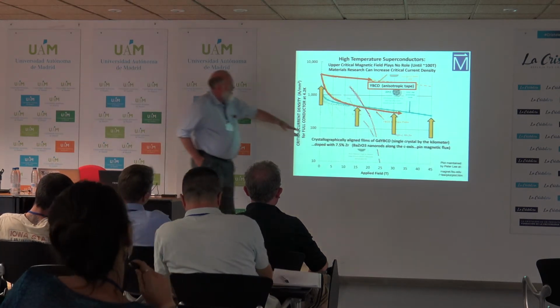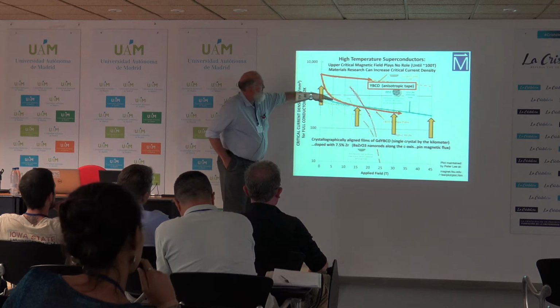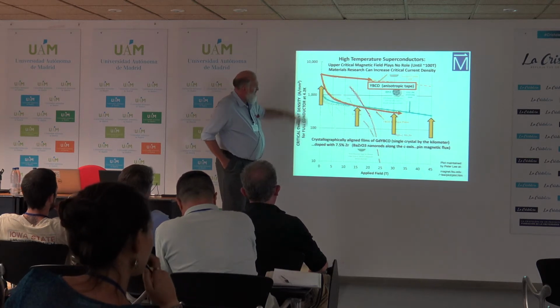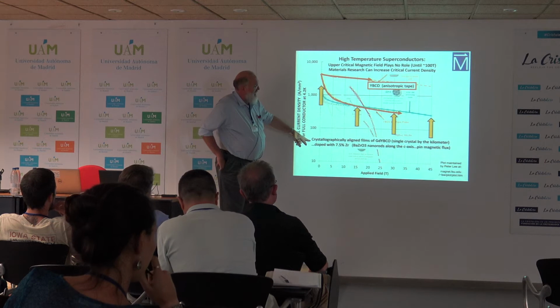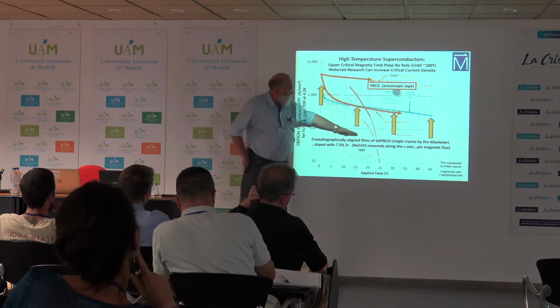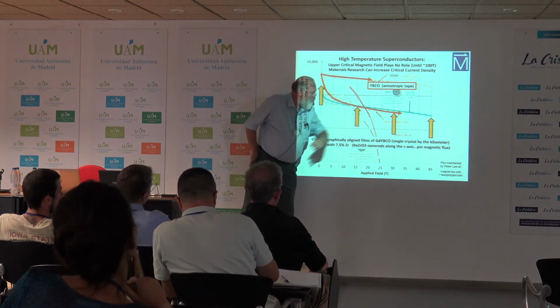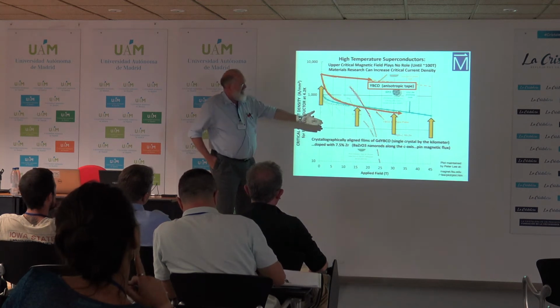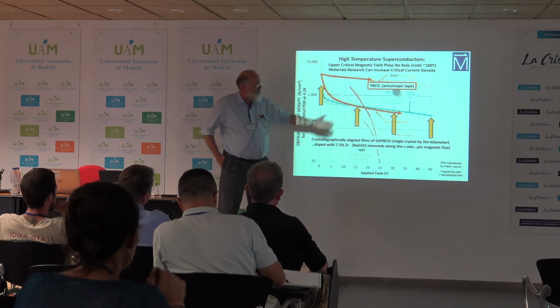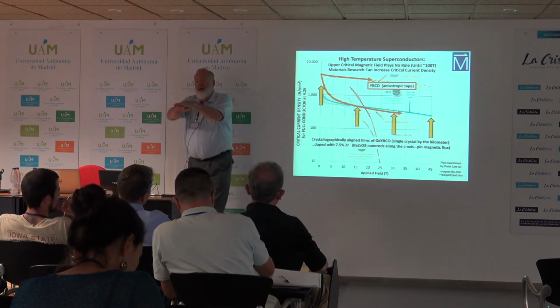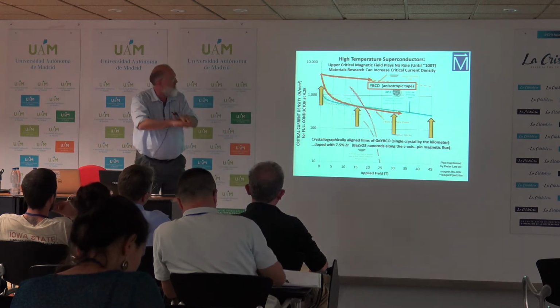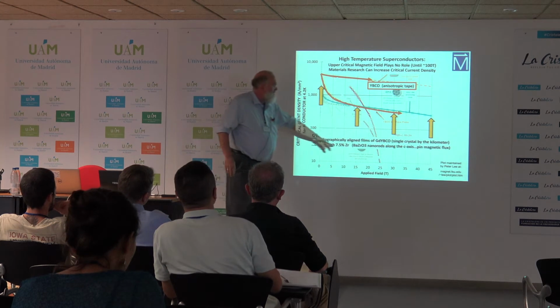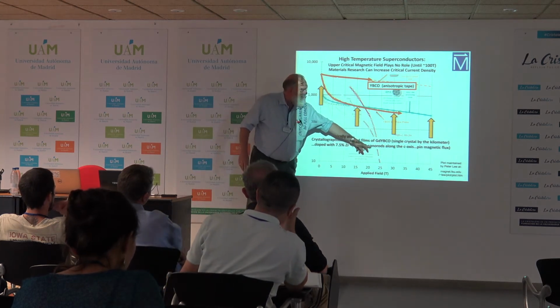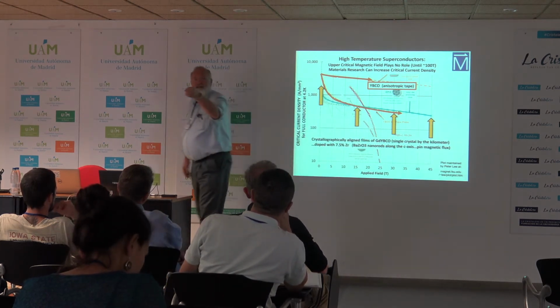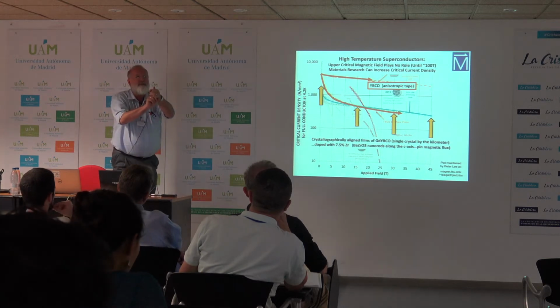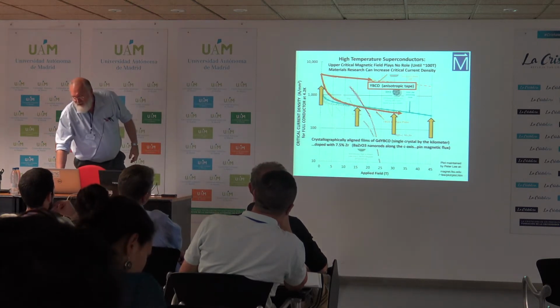And the reason that we're excited in particular is that the value of the critical current density is governed by defects. So they've crystallographically aligned films of gadolinium-doped YBCO. Basically, the tape that we're using in these magnets is single crystal by the kilometer. It's polycrystalline, but they're aligned within a few degrees. They dope with zirconium because barium zirconate makes nanorods of normal state. And that pins the vortices in those small nanorods of normal state.